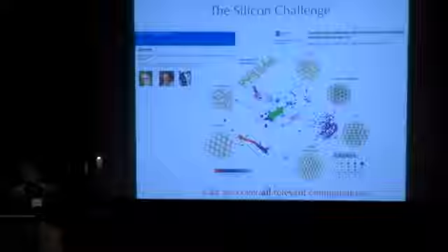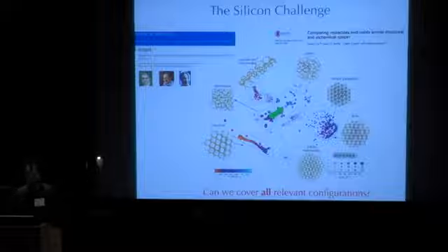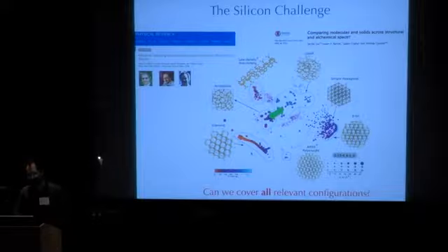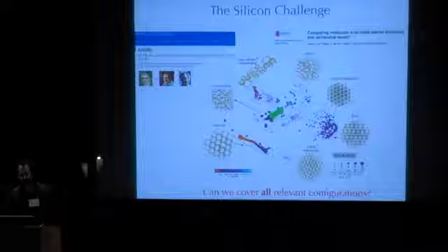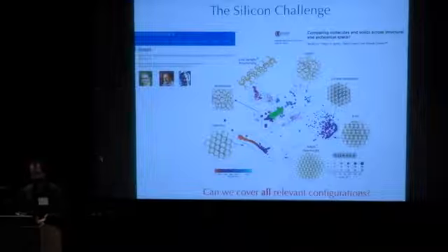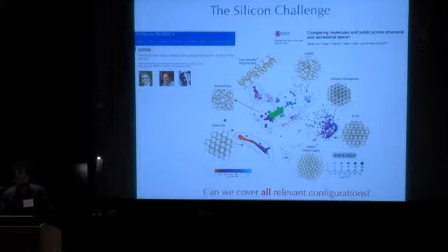Let me draw your attention to these 2 different groups. These are liquid snapshots, and these are amorphous snapshots. Amorphous silicon is a technological material for sensors. In fact, the way I made this map, this is a multidimensional scaling map using the SOAP kernel that I introduced. And what that tells you is that this is a very good sign. It actually separates liquid structures from amorphous structures structurally without any dynamics. And that's new physics already, because people, as we heard yesterday, don't know how to think of an amorphous and a liquid structure independently.